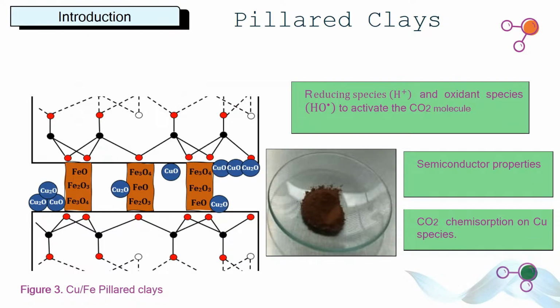What are pillared clays? Well, chemically speaking, they are aluminosilicate layers. Here, you can see this. And then by ionic exchange, we are introducing ion species here, like pillars, chemical pillars, and then copper oxides. By XPS, we have proved that those species are the ferrous oxide, the ferric oxide, and magnetite, and also the cuprous and cupric oxide. What are the advantages of these photocatalysts? Well, I'll be proving to you the different advantages over titanium dioxide from the photocatalysis perspective. But all of them have semiconductor properties, and they facilitate the CO2 chemisorption, mainly the copper species.